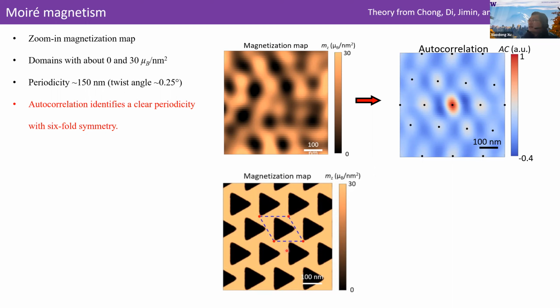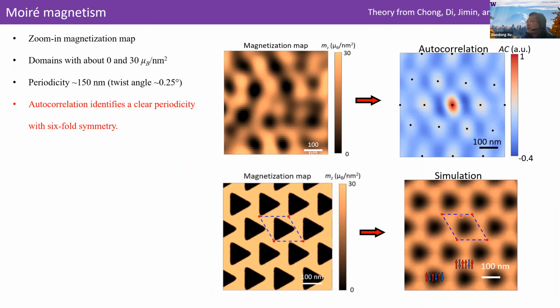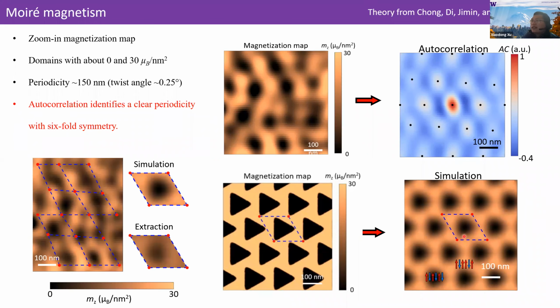patterns. Then we can also simulate what the measurement is. Imagine we use this single spin quantum magnetometry to measure this magnetization map. By considering the spatial resolution and other effects, we can see that the simulation, this is what the measurement will look like if we have this magnetization map. So this is consistent with our data. And lastly, we can also extract the magnetization in a single unit cell, and it's comparable to what we have from the simulations. So I think we have pretty convincing results for this twisted trilayer on trilayer.